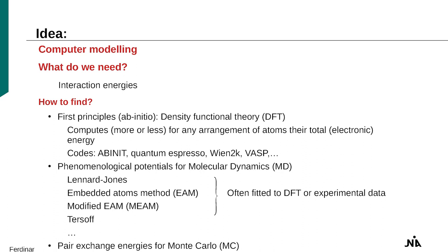A more refined type of interaction are the so-called EAM, or embedded atom method potentials, which allow to implement also many-body interactions. One of the shortcomings of this Lennard-Jones and simple pair potentials is that they don't include third partners in this interaction. In this simple example which I showed, where you have the two atoms interacting, this might depend on a third atom which is sitting here, or maybe even in between. Clear? And this is completely excluded in these simple pair potentials like Lennard-Jones, but to some extent included